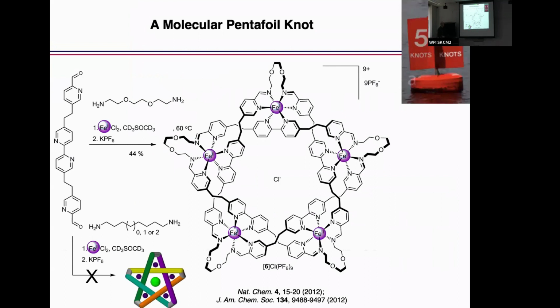your knot. And so we modified Lehn's design to get rid of the bipyridine units from these two end groups and replace them with these single pyridine groups with an aldehyde. And that aldehyde can condense with an amine to form an imine to form the bidentate group that's needed on the terminals. And that is a dynamic reaction, which means we can use much lower temperatures than Lehn used. This occurs at 60 degrees in DMSO, and this is reversible, so it will do the error correcting. And sure enough, if we take this ligand and this particular bisamine, we can form this pentafoil knot in reasonably good yield,